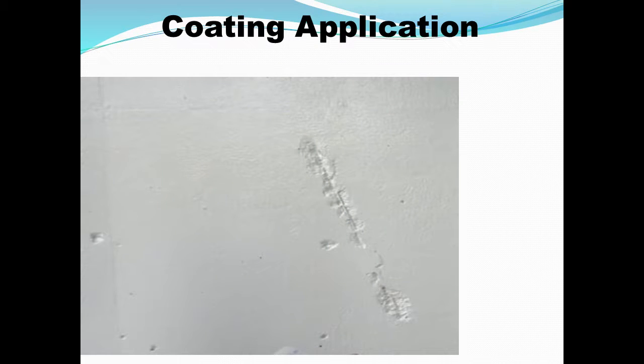For example, here, where there was some steel close to the surface, and it had corroded and popped the concrete off, that had a brush. Probably this spot had a brush and this one. But the one thing I did want to point out here is that we made no attempt, and this was one of the things we're talking about, the user-friendly coatings. We didn't want our crews to have to go out there and fight with pinholes. So it's sort of a measure of how easy your coating is to apply if you don't have a lot of pinholes in it, and we weren't going to take a lot of effort to repair them.